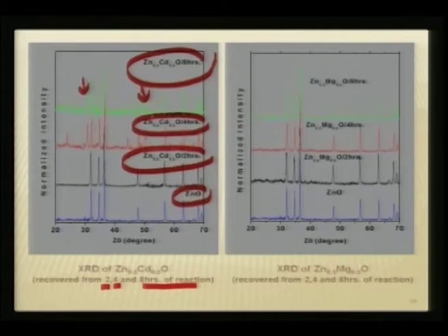What does that mean? This seems to be a kinetic growth, and with more and more nucleation, your cadmium is not actually getting doped into zinc oxide, whereas the cadmium hydroxide first starts nucleating and then starts building up into a crystalline matrix. Therefore, along with zinc oxide, what is actually growing is the cadmium hydroxide particles, which are coming out as nucleated features. So more and more cadmium hydroxide gets nucleated, then it crystallizes as a crystalline phase.